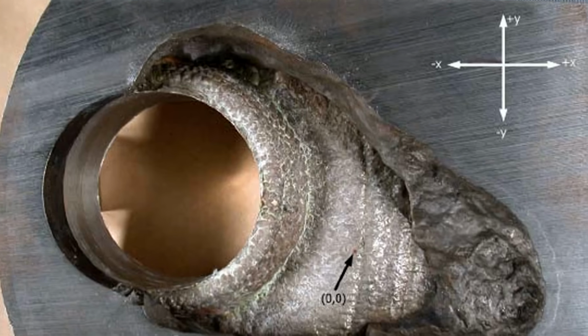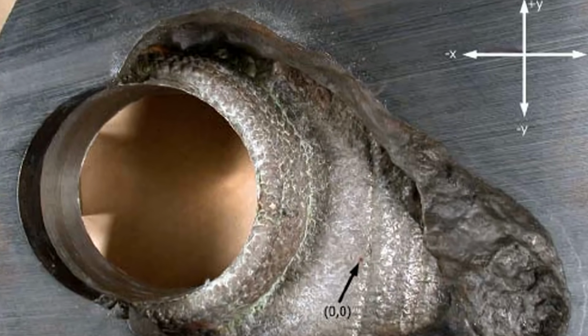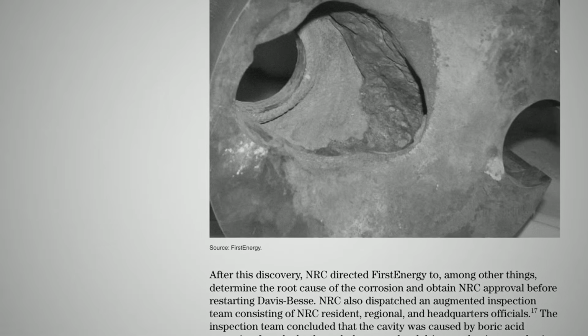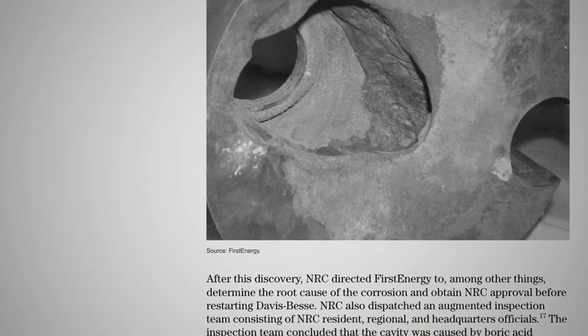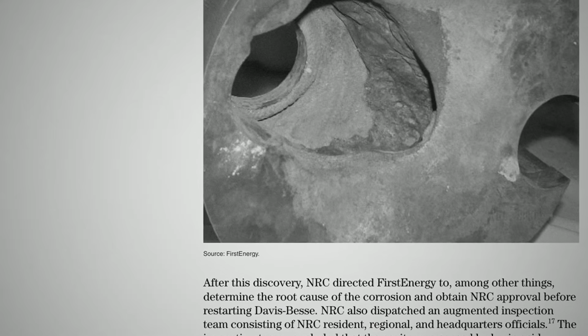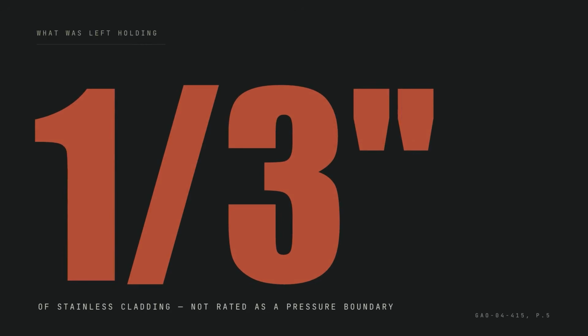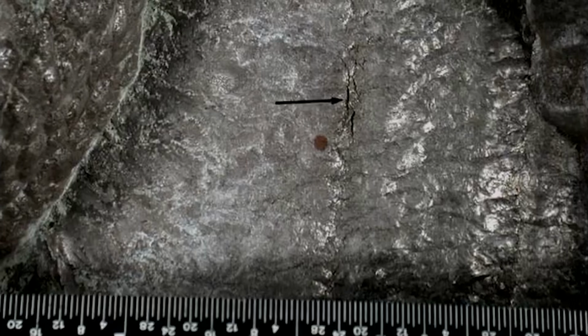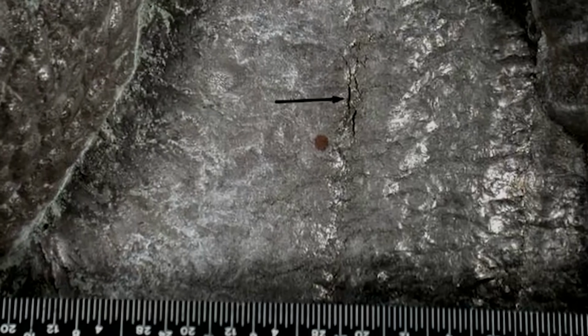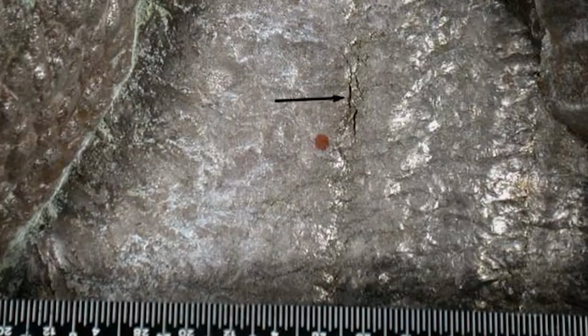This is a photograph of the top of a nuclear reactor. Look at the hole. That cavity is about the size of a pineapple. It goes clean through 6.5 inches of carbon steel. Under it, there was nothing left but a stainless steel liner about 1/3 of an inch thick. Behind that liner sat about 2,000 pounds per square inch of superheated water.